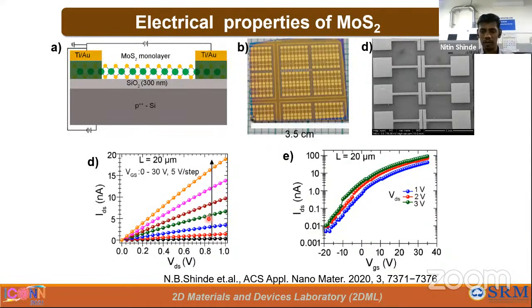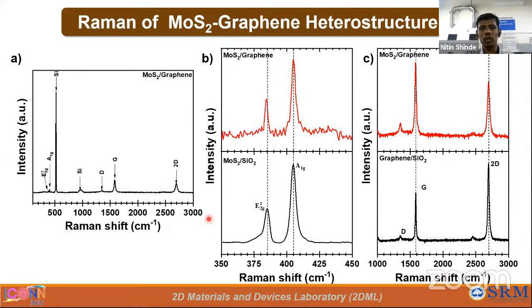Using these parameters, next we fabricated a MoS2 graphene heterostructure. Initially, we transferred graphene on a SiO2 substrate, directly loaded this graphene in the CVD chamber, and directly fabricated MoS2 on graphene. We can see the whole Raman spectra from 100 to 3000. Here E2g and A1g belong to MoS2, and the D, G and 2D peaks belong to graphene, and the remaining ones are the silicon peak.